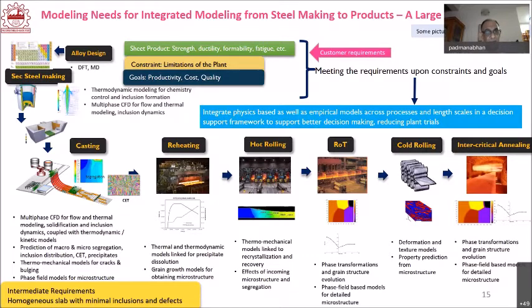And then, when it solidifies, some microstructure gets developed. So that means you have to have phase field models. Phase field is nothing but, if I want to put it simply, it assumes that when a liquid becomes a solid, a sharp interface develops. This is a basic assumption which is necessary. Once the thing is assumed that way, it will be possible for you to work out the energy associated with the interface, the volume, and so on. And this leads to the famous equation developed by John Cahn and his associates. It takes you to the Landau-Ginzburg equation for grand potential, as they call it. That is free energy. This is basically a free energy minimization concept. And you minimize that, and you will develop the kind of microstructure that is developing.